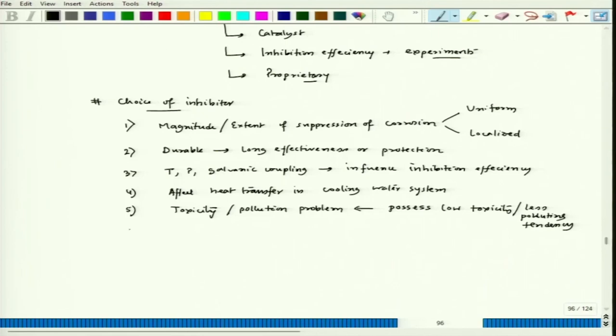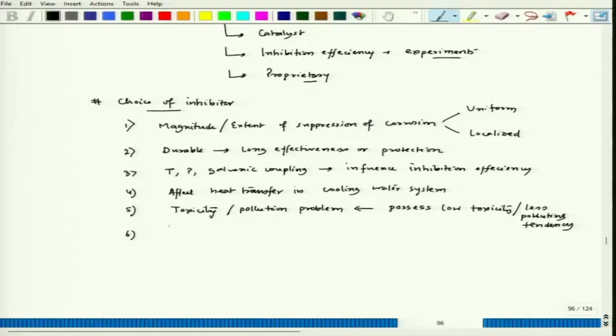Now, finally, many of the inhibitors are very costly. For example, one of the inhibitors which is considered to be anodic inhibitor, molybdate. So, molybdate inhibitors are very costly, but they are very effective anodic inhibitors. They can reduce the corrosion rate to a great extent of steel. So, we have to also look at the cost factor. That cost factor will also decide the durability of its use or the prolonged effectiveness of those inhibitors in reducing the corrosion rate, as well as the dose of those inhibitors. So now we have to also look at dose as well as cost. So that will decide the economic use of inhibitors.